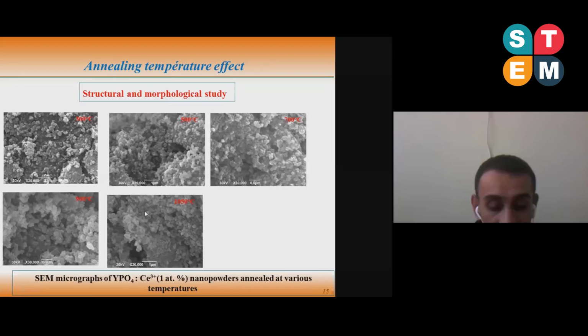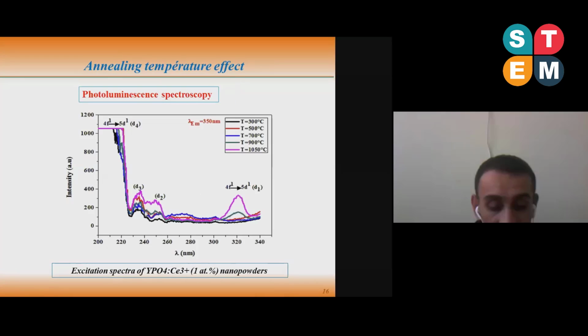The influence of annealing temperature on the photoluminescence parameters of yttrium orthophosphate powder was also studied. In this study, the emission and excitation spectra of the powder are presented. This figure shows the excitation spectra of yttrium orthophosphate doped by trivalent cerium nanopowder. The excitation spectra from all annealing temperatures show similar spectral features with the same position of absorption bands. All the observed excitation or absorption bands are attributed to interconfigurational transitions of cerium 3+.